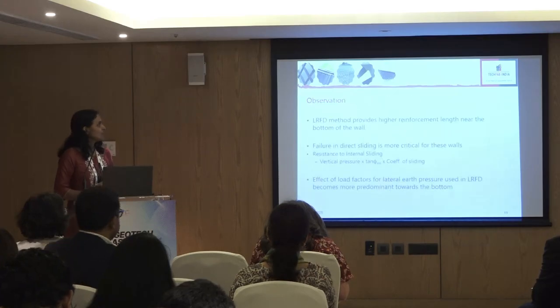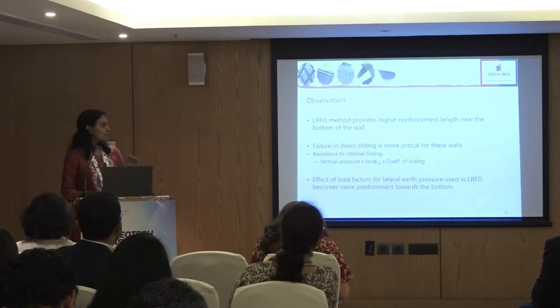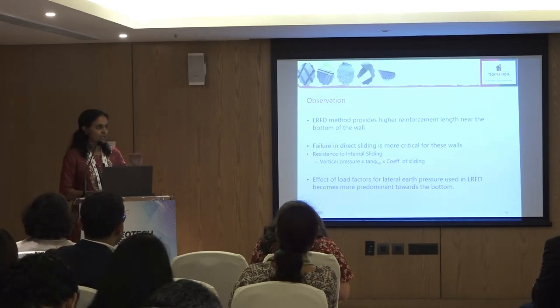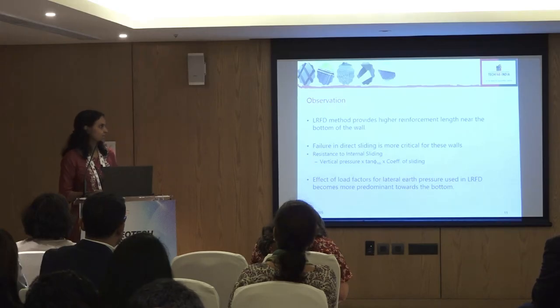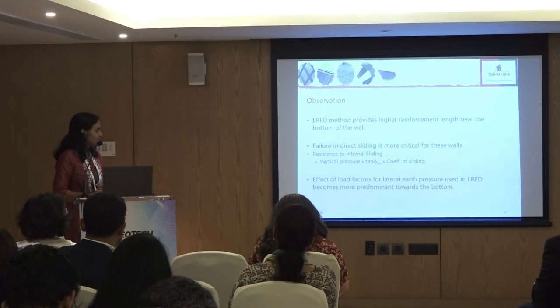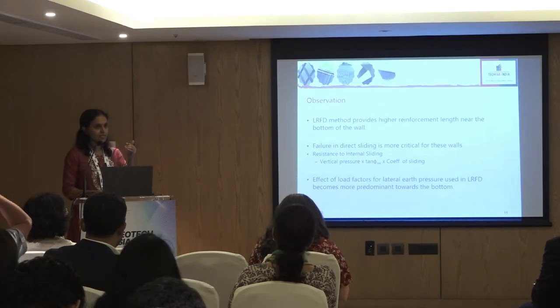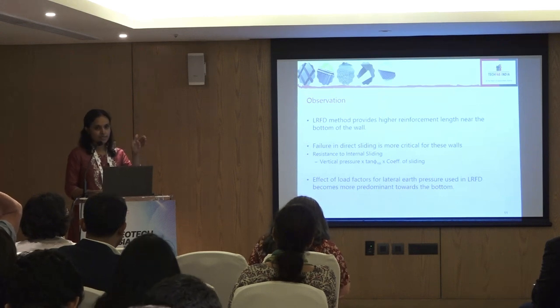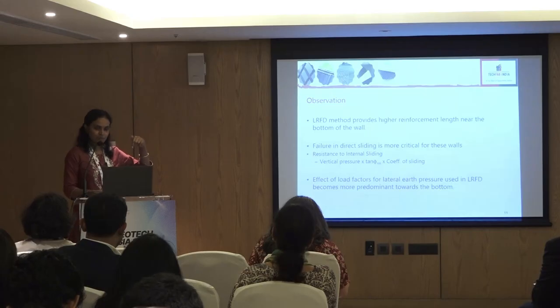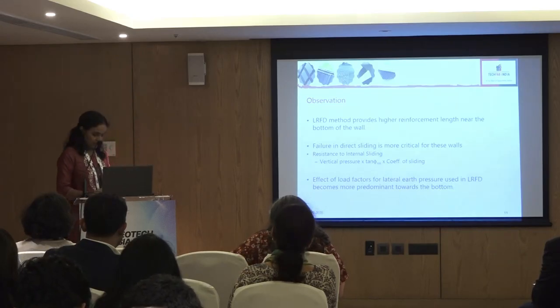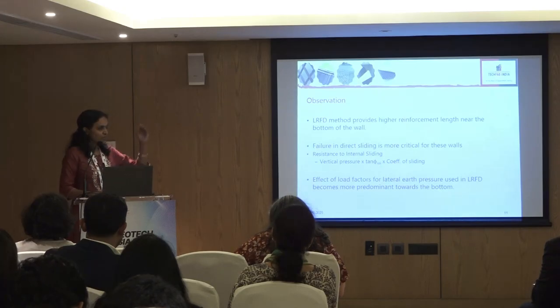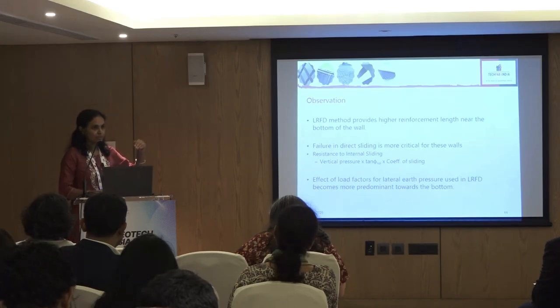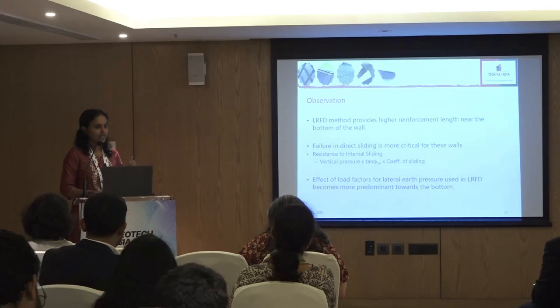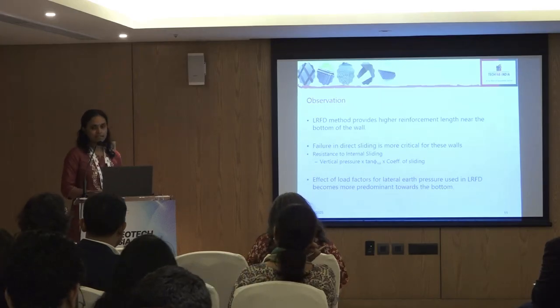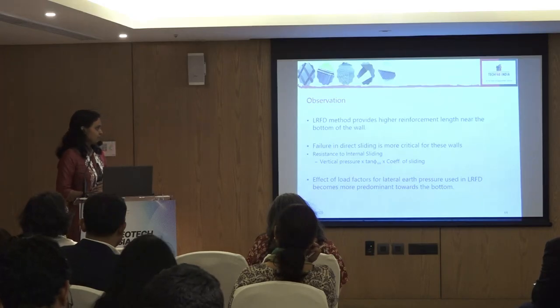Now, as I told, this is because in block geogrid arrangement, we observed that direct sliding is more critical in internal stability. So we can see that in direct sliding, in LRFD method, for lateral earth pressure we are providing a factor of 1.5, whereas for vertical load, we are providing a factor of only 1. Because of this, towards the bottom of the wall, it becomes more critical compared to ASD method. Hence, LRFD method is demanding more length towards the bottom of the wall.